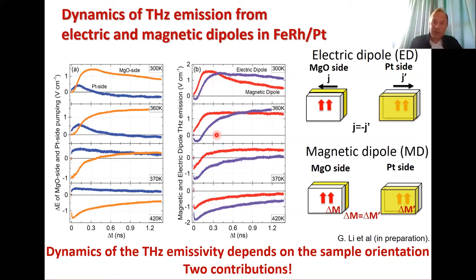Here we are still annoyed by the fact that we have a contribution from ferromagnetic nuclei, the nuclei which were already present in the medium and were then affected by both pulses. Basically, the first pump pulse demagnetized them, and the second pump pulse demagnetized them as well, and this gave us a contribution with a negative sign in the case of the electric dipole contribution. So we wanted to get rid of this in order to be exclusively sensitive only to ferromagnetic nuclei which appeared after the pump one.